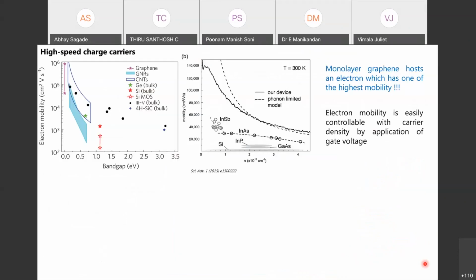So let me tell you now what high-speed charge carriers mean. This is a graph from a paper from 2015, in which mobility of electrons is plotted as a function of charge carrier density for various materials. This dotted line represents the theoretical limit for a particular material. As you can see, very well known and high performance materials are compared here. One of them is indium antimonide, which is known to show one of the best mobilities, in the range of 50,000 centimeters square per volt second at room temperature. Then there are indium arsenide, indium phosphide, gallium arsenide, and of course silicon also.